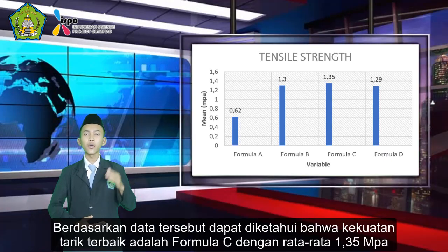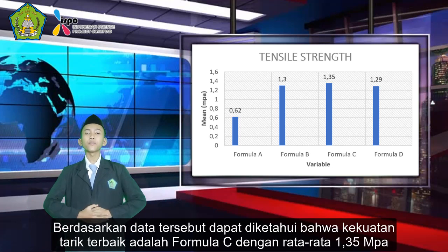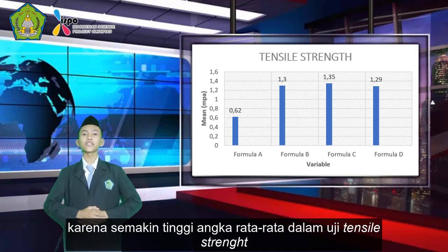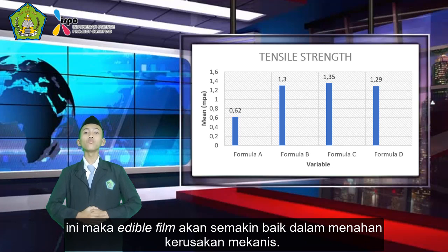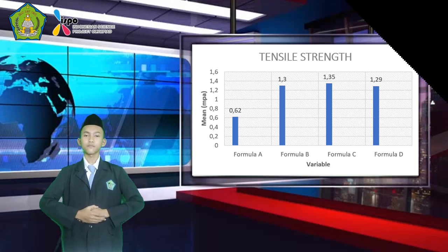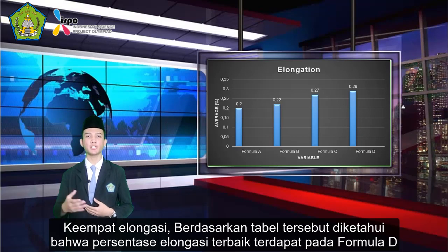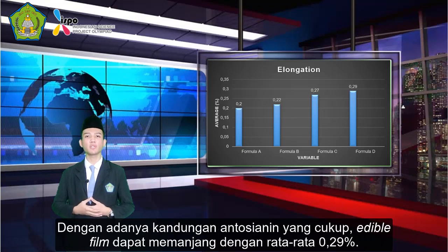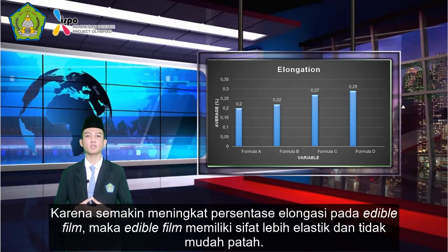Third, the tensile strength. Based on the data, it can be seen that the best tensile strength was formula C with an average of 1.35 MPa. The higher the average value in the tensile strength is, the better the edible film will withstand mechanical damage. Fourth, elongation. Based on the table, it was known that the best elongation percentage was formula D with sufficient anthocyanin content. The edible film can be elongated by an average of 0.29%. Due to the increasing percentage of elongation in edible films, the edible films have more elastic properties and are not easily broken.